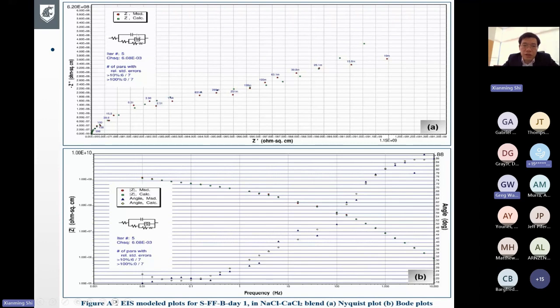So here I mentioned two different interfaces. One is the coating to de-icer interface, and the other one is the metal to de-icer interface. So we can get specific values of these resistances and capacitances, and then from their change over time, we can see whether or not the coating is deteriorating and how fast it's deteriorating, or how fast also the underlying metal is corroding.